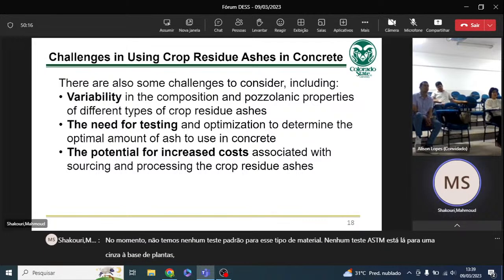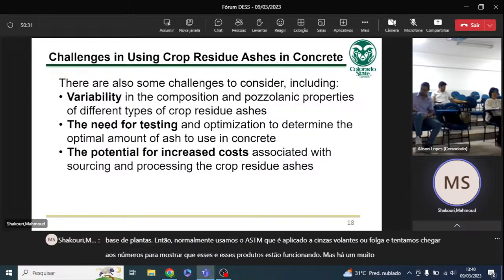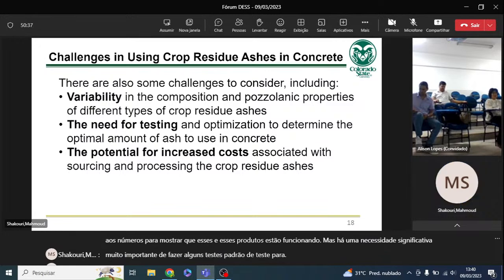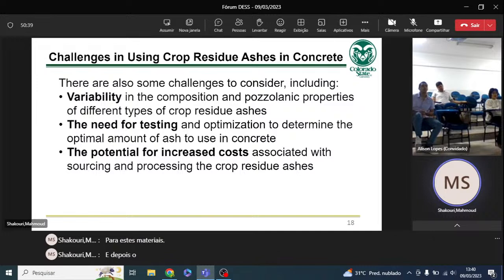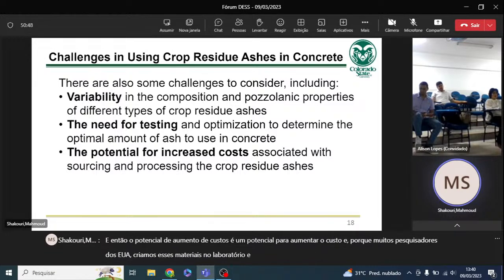So we typically use ASTM that is applied to fly ash or slag, and try to come up with the numbers to show that these products are working. But there is a very important, significant need for making some standard testing for these materials. And then there is a potential for increased cost, because a lot of us researchers, we create these materials in the lab, and in the lab everything is more expensive than if you have mass production. So there has to be some cost analysis to make sure that it's beneficial.